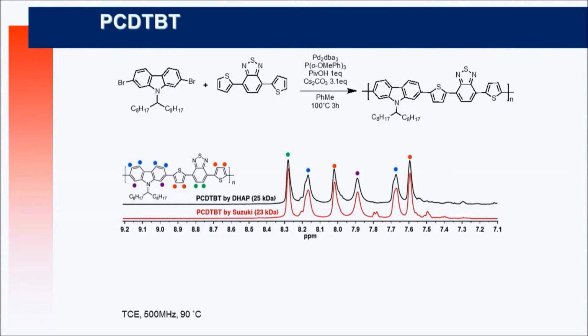This important PCDTBT polymer was prepared by direct arylation polymerization, for instance. Usually we use the Suzuki coupling. Now we use this dibromo carbazole, this unit with a lot of CH bonds. If you're very careful, it's quite selective. Those protons here will react first, and you get comparable NMR spectra and comparable UV-visible absorption, comparable hole mobility, and we will see soon if we get comparable solar cells from those materials. But clearly we will decrease the cost of fabrication of those polymers.